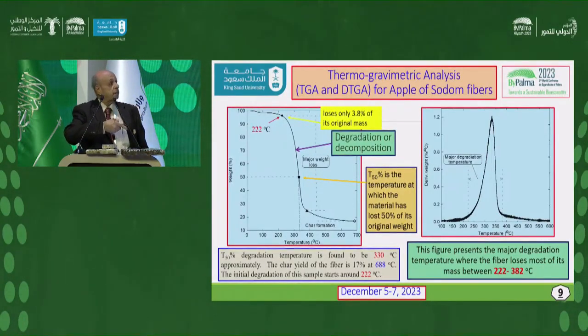This is the thermal degradation of the apple of sodom fiber. Okay, it's stable up to 222 degrees centigrade. Okay, and at 50% weight decrease, it is at about 300.